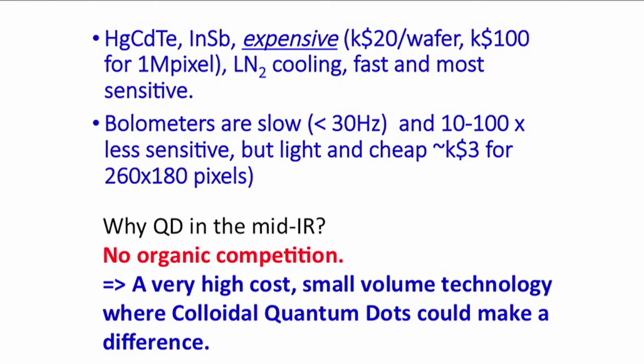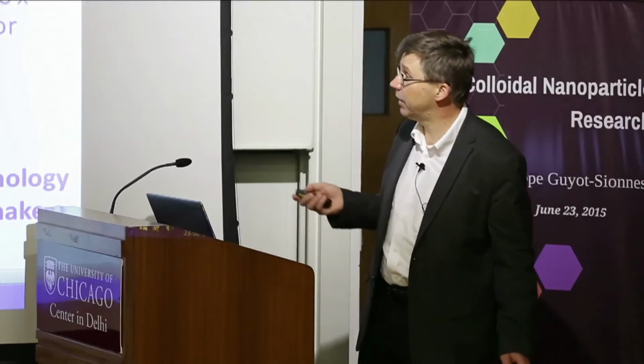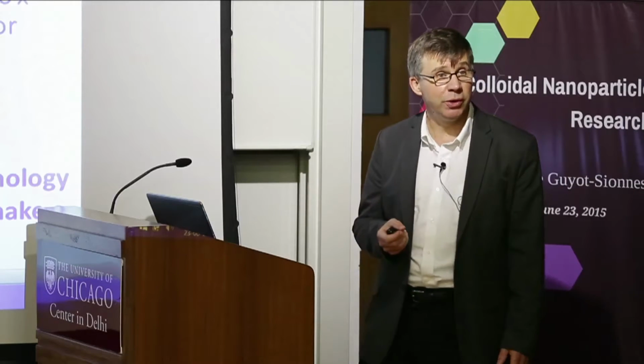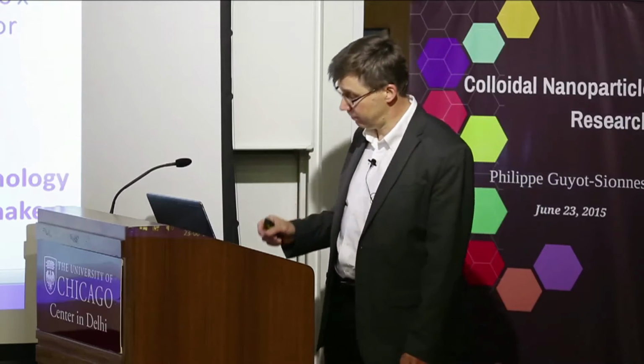They're also very fast. Now, there's a very cheap technology which has evolved wonderfully over the last few years, which is bolometers, but they are slow. So if you wave your hand like this, you just see a band that is blurred. They're also not as sensitive, about 10 to 100 times less sensitive than the quantum detectors. And they're much cheaper. So nowadays, something like this would be about $3,000, but you can get even cheaper cameras, not video cameras, but cameras that you can apparently add to your cell phone for a few $100s, which have about 100 by 100 pixels.